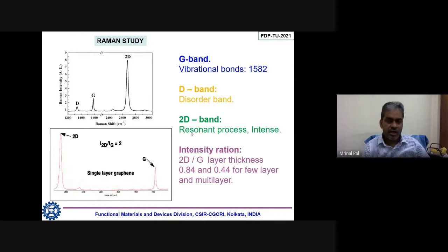In case of Raman study for a graphene material, you will find 3 important peaks. One is called the D peak, another is G, and the other one is 2D. The G band is nothing but the graphene vibration, the CC bond vibration, which comes around 1580. So that is the G band, that is intrinsic. D comes from disorder. As this is a 2D structure, I have mentioned that there remain a lot of defects. So the D band is representative of the defects, and the 2D band is a more intense band, and that comes because of resonance, and that is again an indication of these